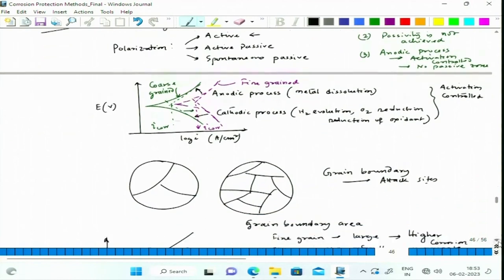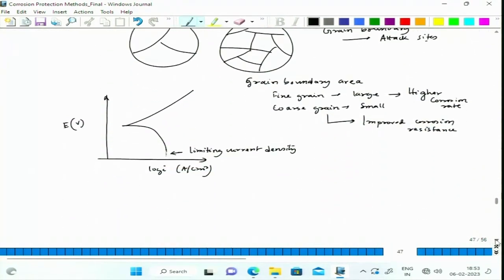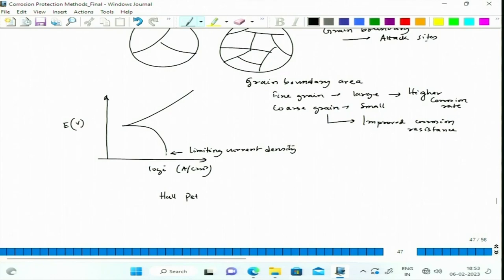But remember, as we are indicating, we have to find a trade-off. In order to get better corrosion resistance in terms of grain size, we must not make it coarser, because if we make it coarser, we are actually losing toughness. As we know, finer material shows better toughness, and for that we know the Hall-Petch equation is active. The Hall-Petch equation shows that the flow stress is inversely proportional to the square root of the grain diameter, where d is basically the grain size in terms of diameter.